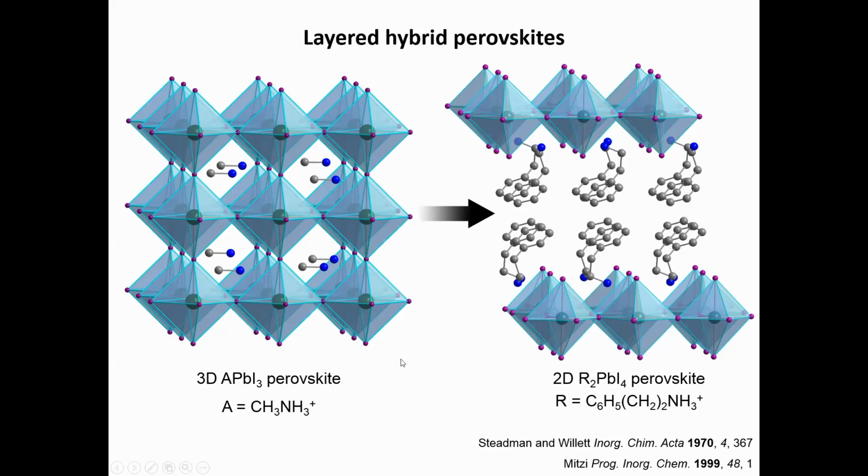In another research effort in my group, we showed that 2D perovskites can make solar cell absorbers which were much more moisture stable, simply because this larger organic molecule is more hydrophobic. So they're not super stable. They're not as stable as the oxides, which you can heat in a furnace at 1500 degrees. Things that form in solution also come apart more easily. But it depends on the application. You can encapsulate this material, and even the white light emitting materials, like we put it on an LED and excited it for a month under inert atmosphere. It was fine.